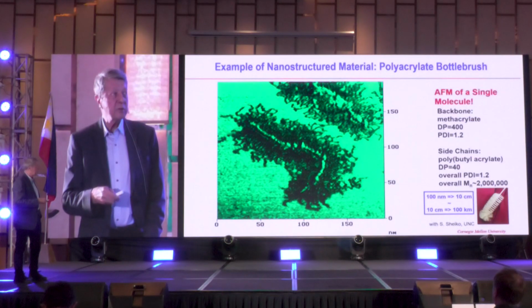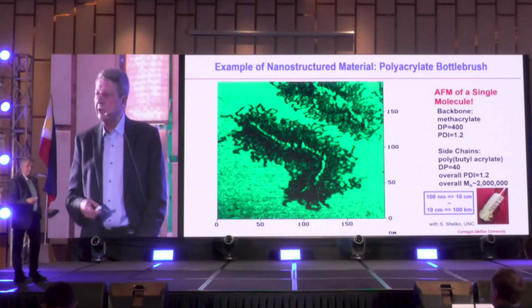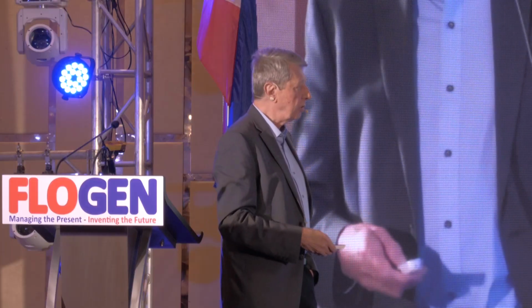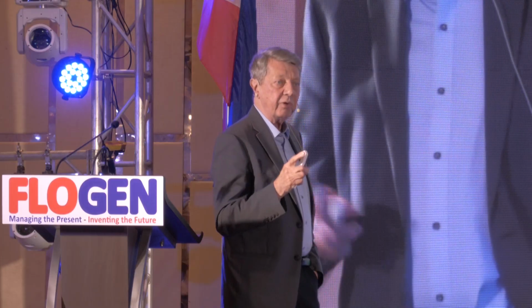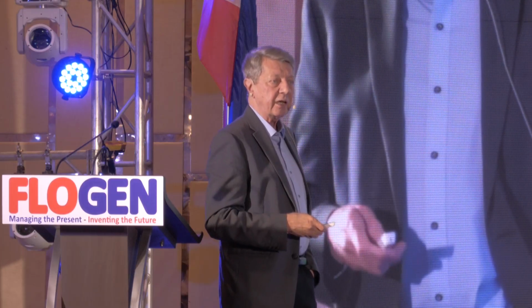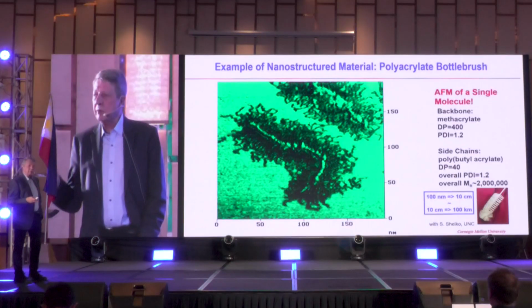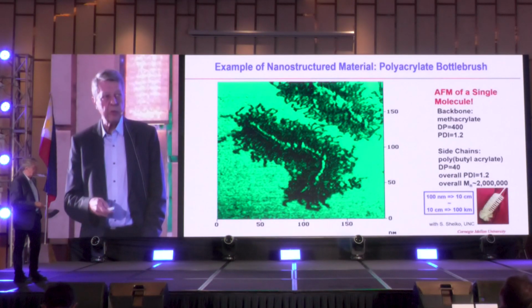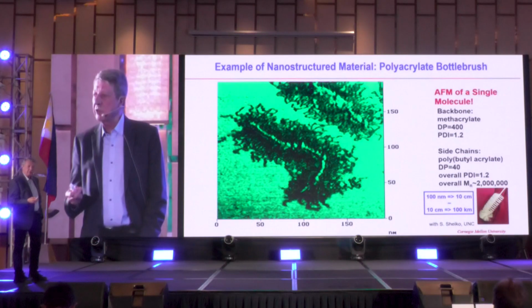And because of that, you can really image this material by using atomic force microscopy. You can count how many side chains you made. They are called bottle brushes because they are extremely densely grafted. Every quarter nanometer is one side chain. And they sometimes have amazing properties because polybutyl acrylate is very, very soft. It has a glass transition of minus 50 degrees, so it's a liquid. If you put them on a surface of mica, they stick to mica.